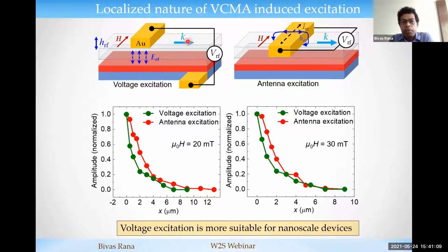And then we compare this with the antenna-induced spin wave. We send current through an antenna, and that generates an Oersted magnetic field. Here you can see this Oersted field is not confined right underneath this conductor. That means the effective excitation area is larger than the width of the conductor. When we measure the amplitude as a function of propagation distance, shown by the red dots, you can see the effective decay length is larger than for the voltage-induced excitation. Especially the first couple of points do not exactly follow the exponential decay trend. So I can conclude that this voltage excitation is more suitable for nanoscale devices, because you can really shrink the size of the device and localize the excitation area underneath this gate electrode.